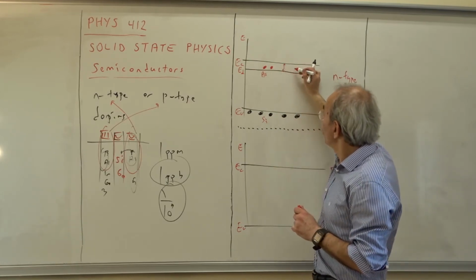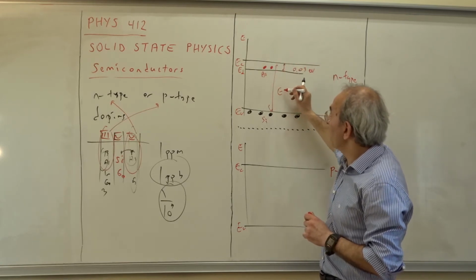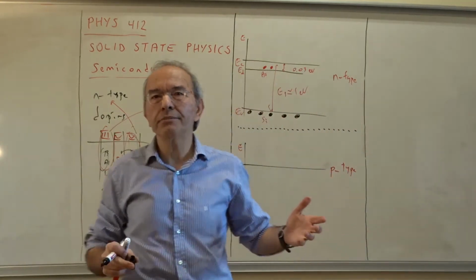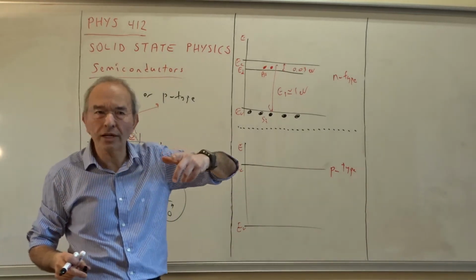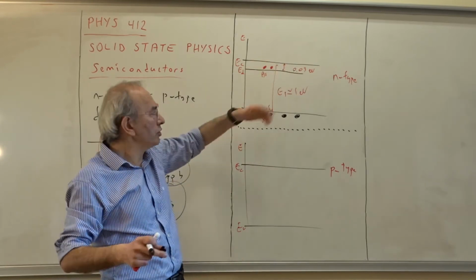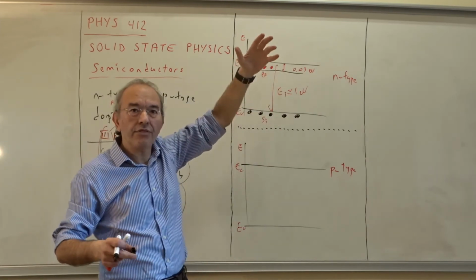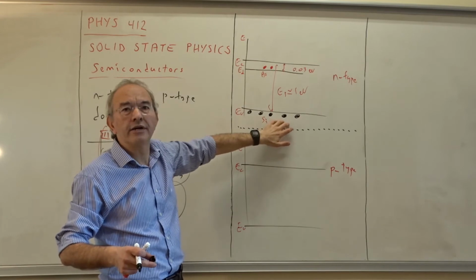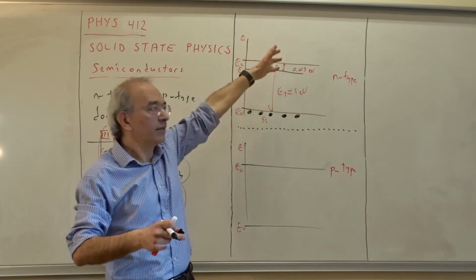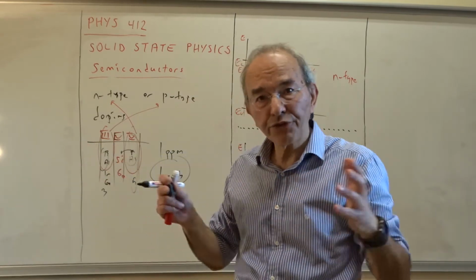So this is on the order of 0.03 electron volt, but this whole gap is approximately 1 electron volt. It is 1.1 electron volt for the silicon. Remember, in the previous problem we used it as 1.1. So this is 1 electron volt, this is 3% of it. Of course, it is much more readily excited to the conduction band, and these electrons coming from the arsenic atoms are already wandering around freely in the conduction band.